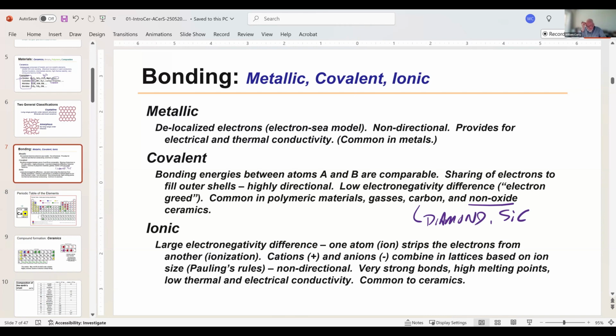Ionic bonding, which is most common in oxides, we have a large electronegativity difference. And what that means is that one atom will steal the electron from another one, okay? And interestingly enough, the one that it steals from is very happy to give up that electron. But what that does is it creates a very strong bond, okay? And the lattices that we generate typically are relatively isotropic in that these bonds tend not to be directional because it's essentially stealing an electron from another. The consequence of ionic bonding is very strong bonds, high melting points. These materials have very high melting points, but also because the electrons are strongly held by those ions in that structure, you have low thermal conductivity and low electrical conductivity. And this is where we are with ceramics, okay?